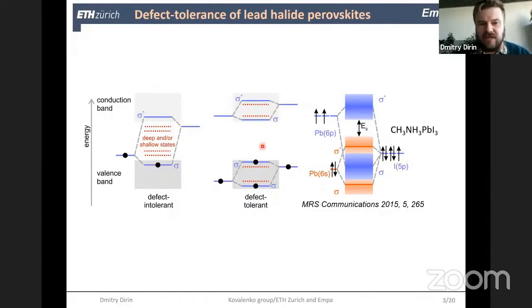But at the same time, we can imagine a hypothetical case. Then the top of the valence band and the bottom of the conduction band are formed by antibonding and bonding orbitals, respectively. In this case, most intrinsic defects, such as vacancies or dangling bonds, will not create trap states within the band gap. They will create states only within the valence band and conduction band.